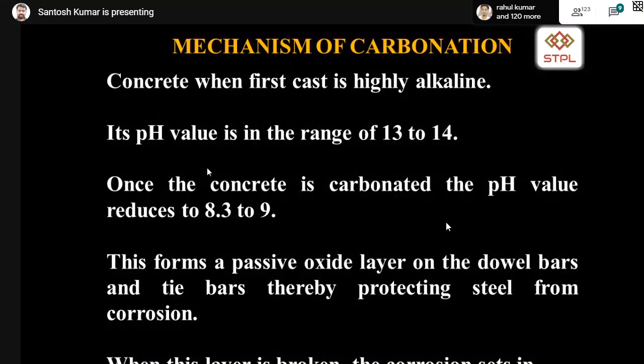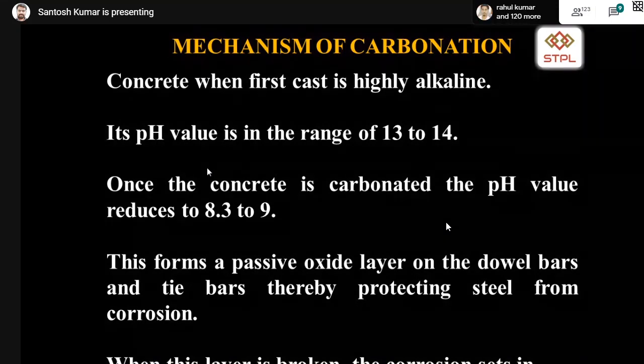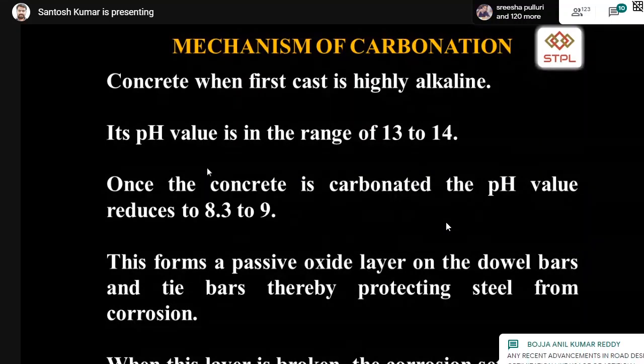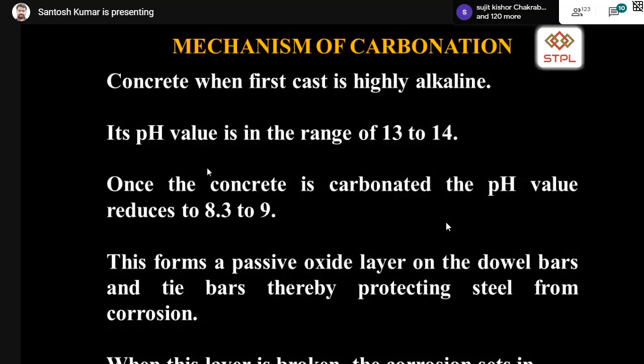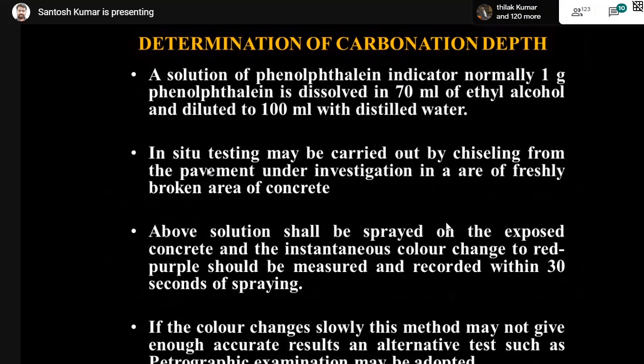This forms a passive oxide layer on the dowel bars and the tie bars, thereby protecting the steel from corrosion. If your concrete is highly alkaline, it protects the dowel bars and the tie bars. If the concrete is not alkaline, it is carbonated, this layer will be broken and the corrosion will set in. So there is a test which can determine the depth of carbonation in your pavements.